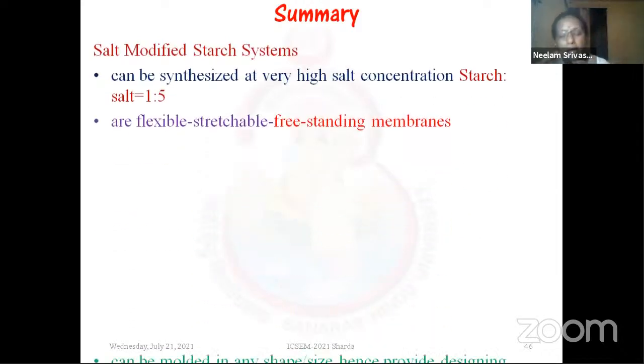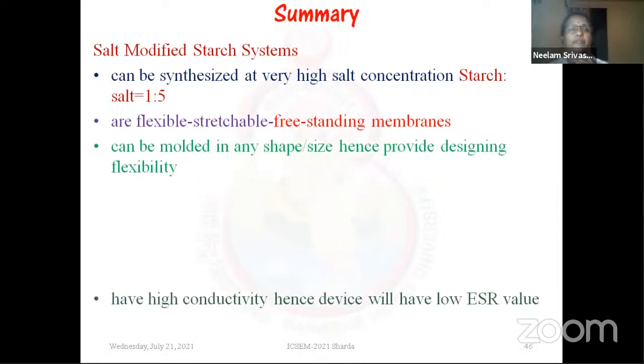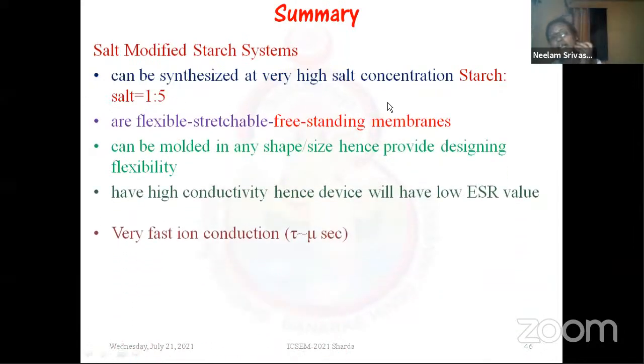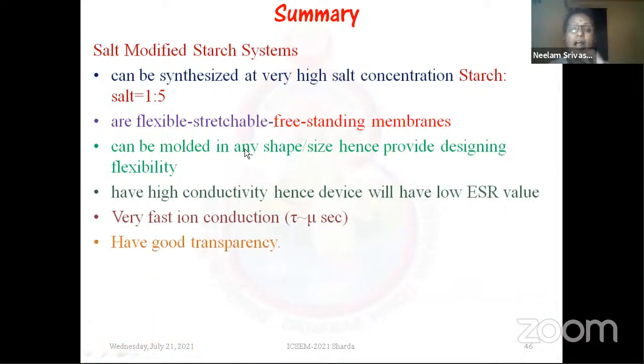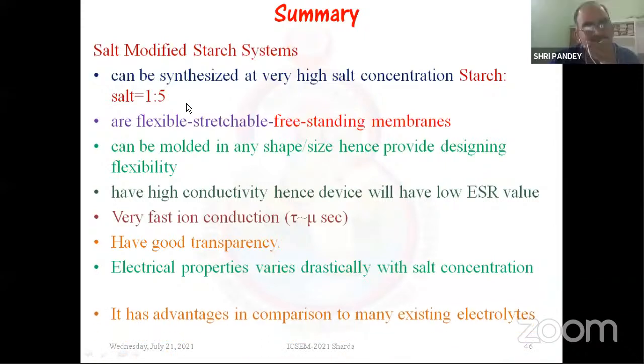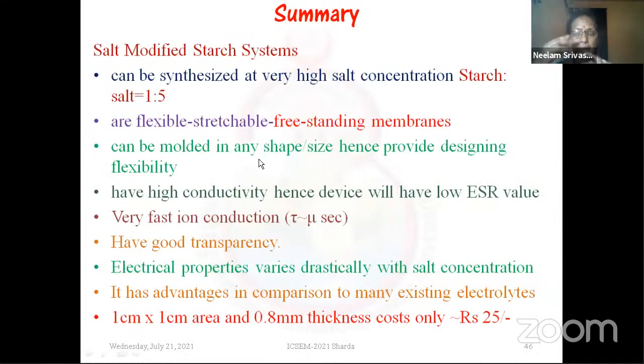So if we summarize our result, we can say that the salt-modified starch systems can be synthesized at a very high salt concentration. You can reach even higher than a 1:5 starch to salt ratio. We studied till 3 because of mechanical problems. They are very flexible and we don't have systems to handle that. Otherwise you can measure them also. They are flexible, they can be molded into different shapes and sizes, have high conductivity, low ESR, very fast ion conduction, good transparency, and electrical properties vary along with the salt concentration, so you can mold them according to your requirement.